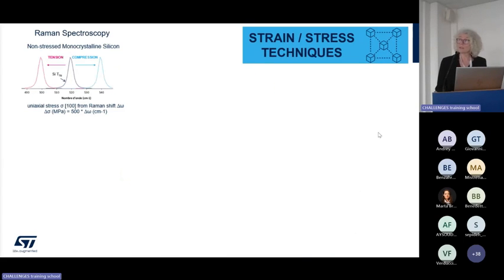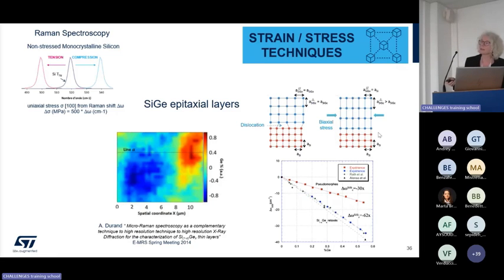And with Raman, of course, I'm not going to go over everything, everyone knows about Raman, for silicon at least. For silicon germanium, it's also very nice to use Raman for mapping. This is the silicon germanium epitaxial layer in top view, so X and Y in a sense. And here you can have local information about the percent germanium modification in this layer. So it's not very uniform in this case, but it's direct information.